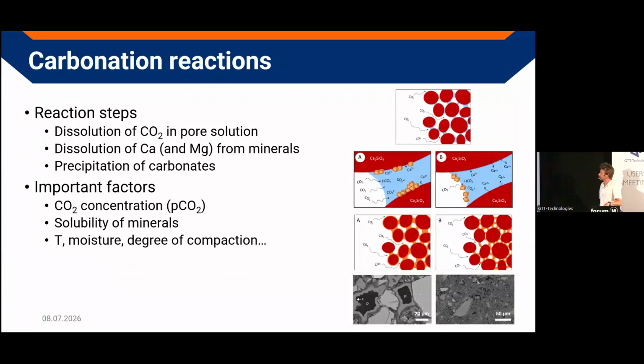Yeah, a bit more in detail about the principle. What are the reactions actually that are occurring? So you have your calcium silicate minerals. You shape them into this kind of product with some moisture. Then you introduce CO2 in a certain reactor. The CO2 goes into the pore solution, and then this also acidifies the pore solution a bit, which makes these calcium silicates dissolve a bit. You have your calcium as well in the pore solution then, and then you have your carbonates and your calcium together, which can precipitate the calcium carbonates, similar for magnesium. And then that can grow your microstructure into something that is hard.